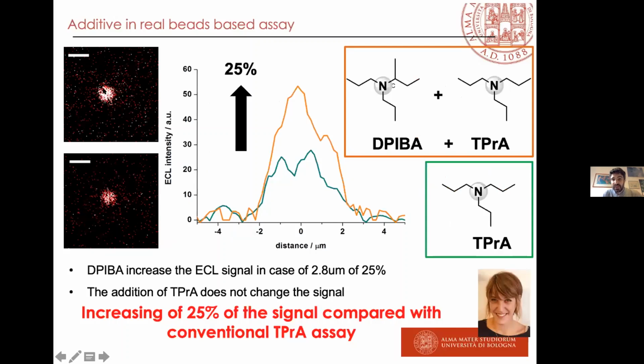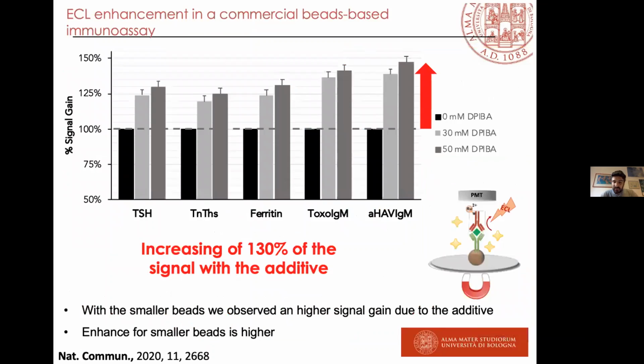And here you can see the beads with the additive, with this different amine, and the beads without this different amine, and you see that we have an increase of 25%. So it means we are enhancing the mechanism more efficient in the close proximity of the electrode surface. Okay, let's move to the real application, because our idea is to optimize the mechanism for a real application.